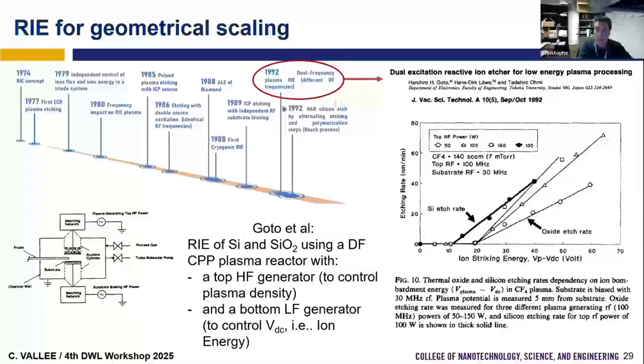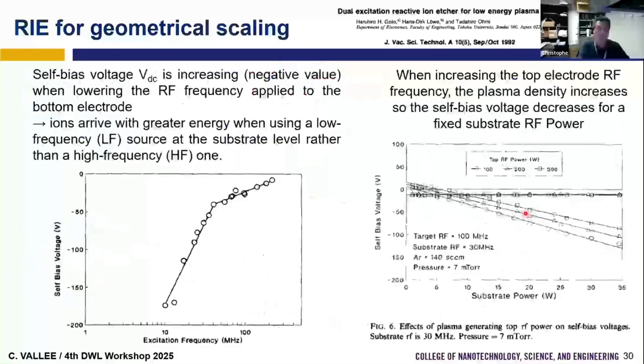And here we have the first paper where people try to use this idea of doing a plasma array with two different radio frequency generators, from Goto, where they use a high frequency generator at the top to control the plasma density and a low frequency bottom generator to control the DC self bias and the ion energy, and they study the etching of silicon and silicon oxide using this system with a dual frequency process.